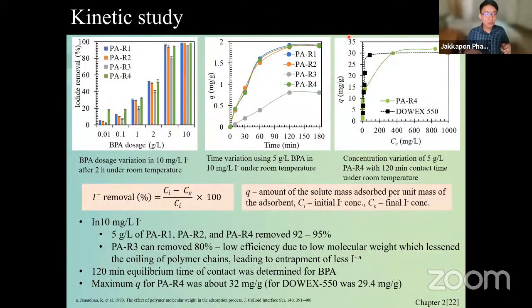Now, just imagine I have already removed the iodide. You see that the dosage that we use is about 5 grams per liter. The time it takes to remove this 10 milligram per liter of iodide is about 120 minutes, okay? It takes quite a long time, but actually it's only about 2 hours. And the efficiency goes up to about 30 milligram per gram.